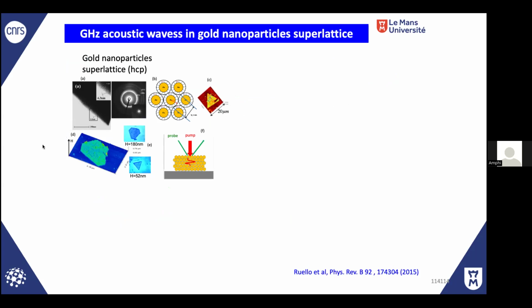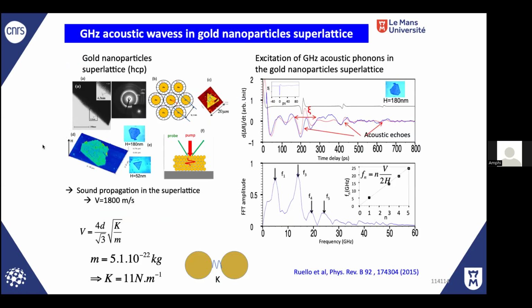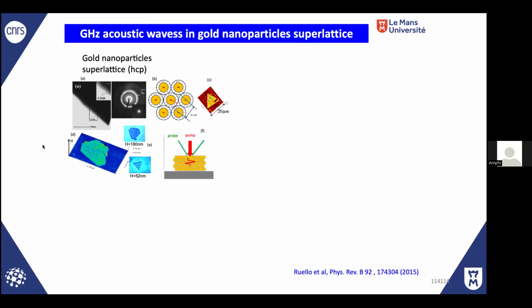And by just looking at the propagation of these coherent phonons, the signals are quite complex, but to simplify, you can measure the time of flight of coherent acoustic phonons in such a system. And the time of flight is related to the sound velocity, and the sound velocity is related to the stiffness. So by looking at how these coherent phonons propagate in such a nanostructure, you can measure directly the bond stiffness between particles. This has been done. We did it as well. But basically, you can do the same thing.